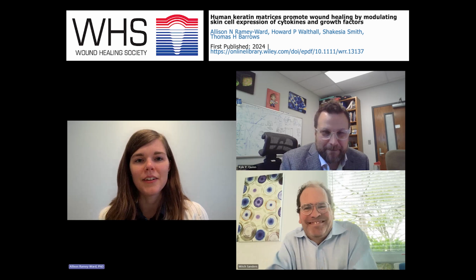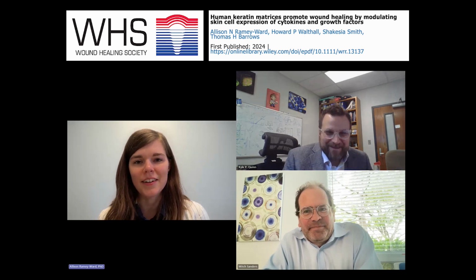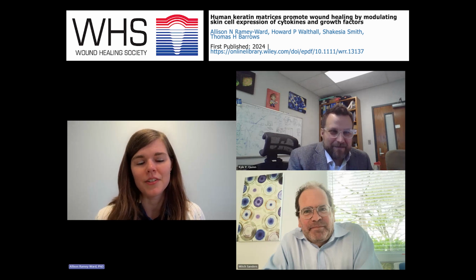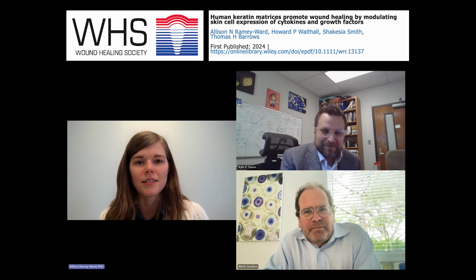Yeah, so our keratin is actually sourced from human hair. We literally collect hair clippings, and then we use a process based on the Shindai method, which is a reductive extraction. It breaks down the disulfide bonds that are so abundant in keratin and give it that mechanical strength we know it for. It puts it into a liquid form that we then cast into our matrix and allow it to recross-link to create the solid products.